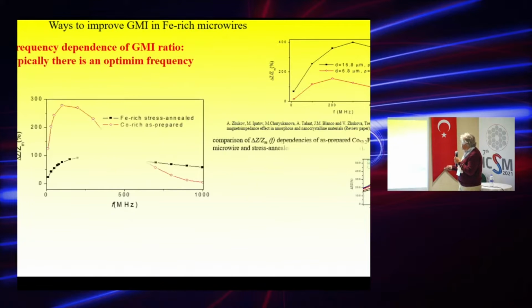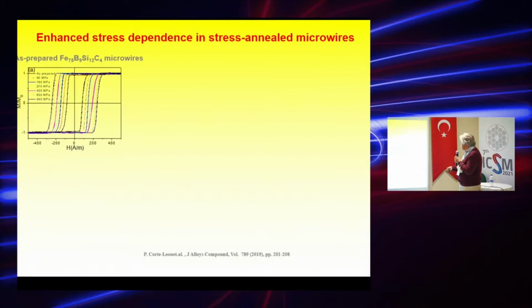Another advantage of these materials: if we compare with cobalt-rich materials, this is the frequency dependence of the giant magnetic impedance ratio. For cobalt-rich materials at low frequency it is still better. But in the higher frequency region, these iron-rich stress-annealed samples become better than cobalt-rich materials. In this case, we plotted the maximum giant magnetic impedance ratio for different frequencies, and we can observe the dependence.